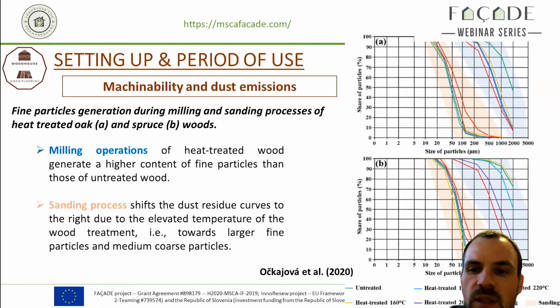We can observe on the graphic on the right that we have the sanding process in pink colors and the milling process in blue. According to the color line, you have the different treatment intensities. We can observe that during the milling operation, heat treated wood generates a higher content of fine particles than native wood, and this content of fine particles increases according to the intensity of the treatment process. However, we can observe the contrary result during the sanding process, where heat treated wood emits lower fine particle content than untreated wood. So additional attention needs to be considered during machining of thermally modified wood.